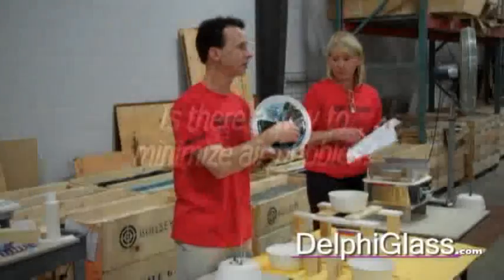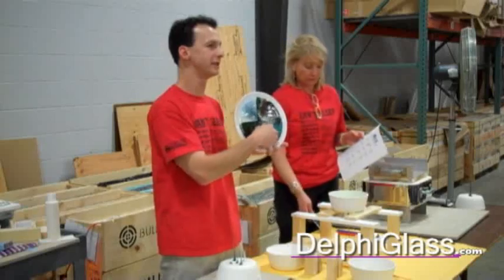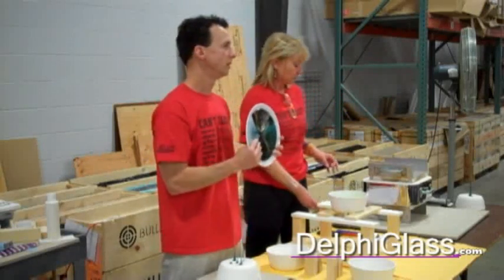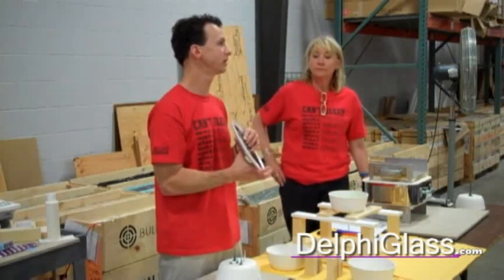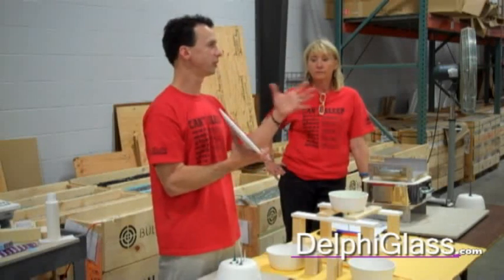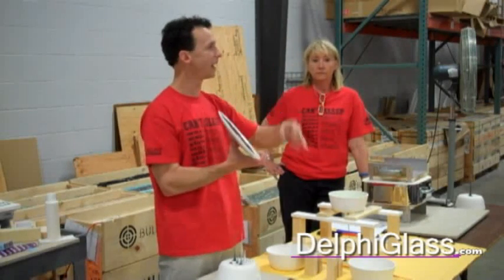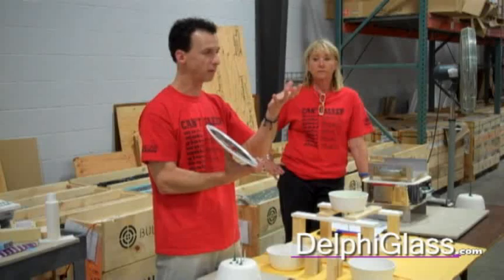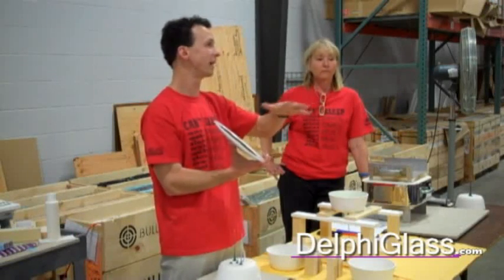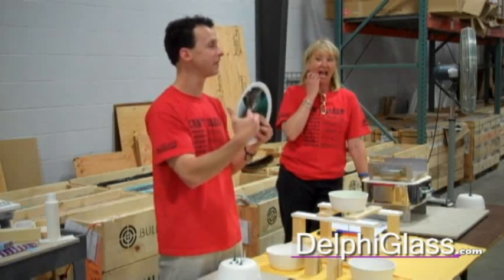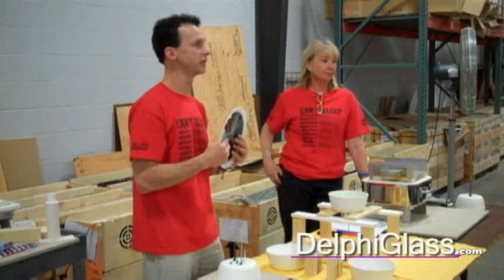To control this, eliminate or minimize air bubbles, you could soak it longer. It really has to do with once you've got it up to 1600 and everything's pouring out of the pot. If you hold it long enough, all those bubbles will come to the surface and pop and then smooth back over. In fact, some of these have popped on the surface. It's firing schedule stuff.